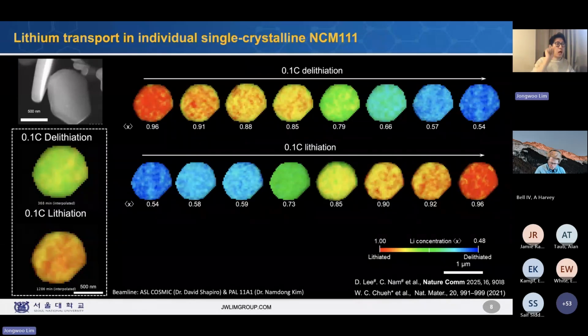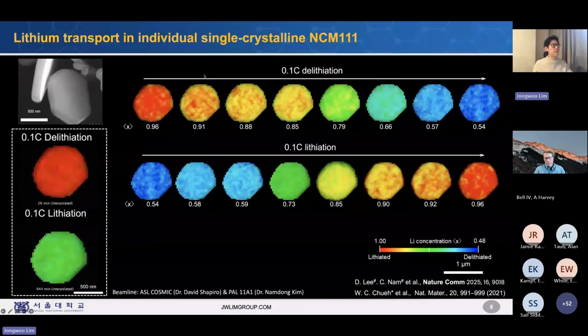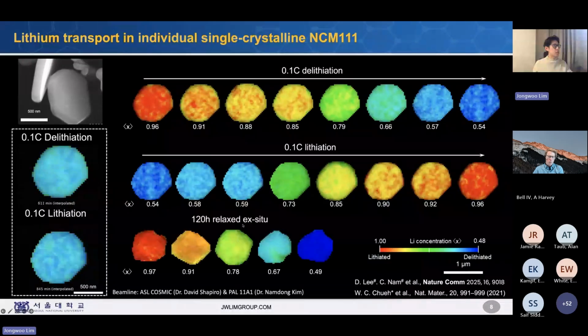However, if you look closely, it's not simply flat while increasing or decreasing lithium concentration. There's some random fluctuation you can notice in the particle here. There's some yellowish area, some green area, some brown, and some blue area. Of course, if you let it relax for many days, thermodynamics will take care of it. Lithium concentration has to be flat, homogeneous across the particle.